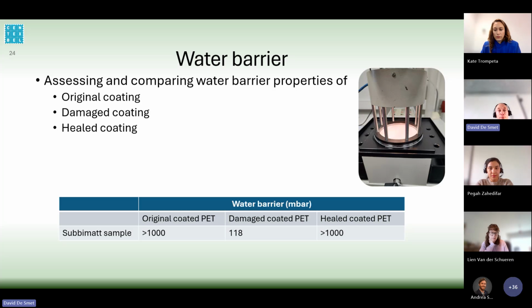Of course, also the water barrier properties are important, and therefore we are also assessing and comparing the water properties of an original coating, of a damaged coating, and then of the damaged coating after healing. So this is also done here for the SUBBIMATT sample. Originally we had a polyester coated with the self-healable PU. Originally the water barrier was minimum 1000 millibars, so this is the maximum value which we can measure.